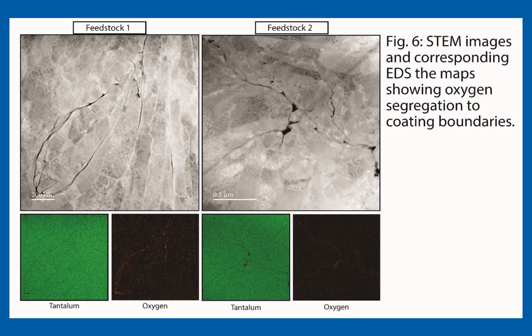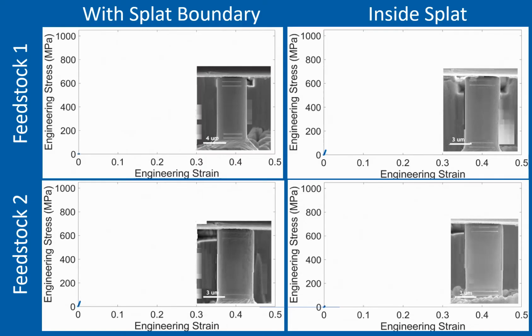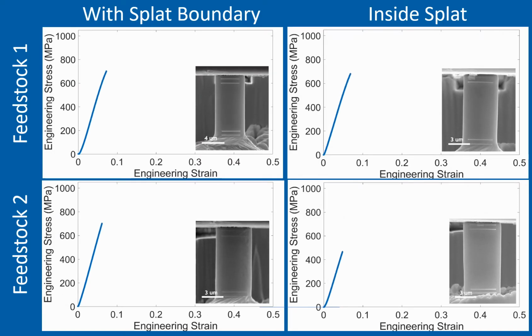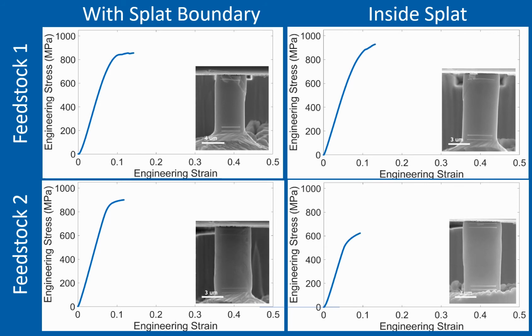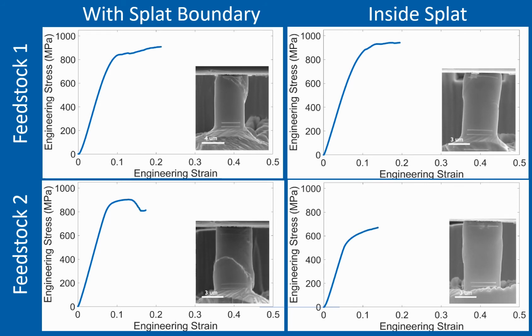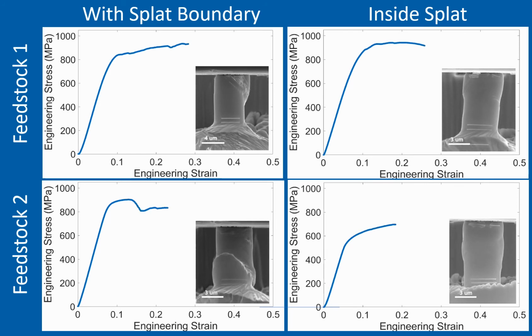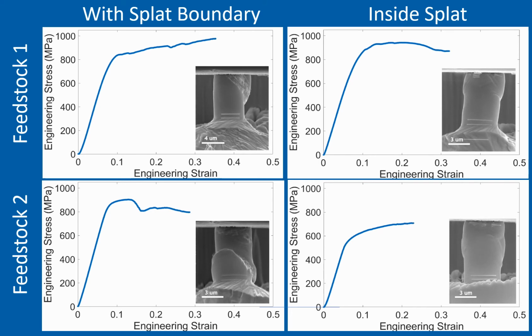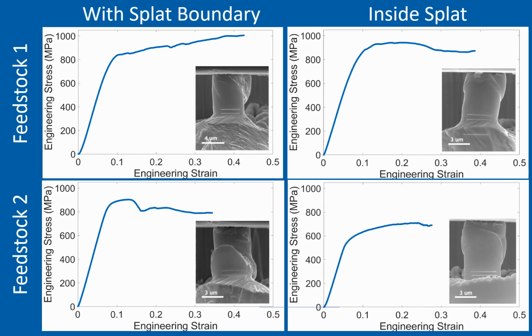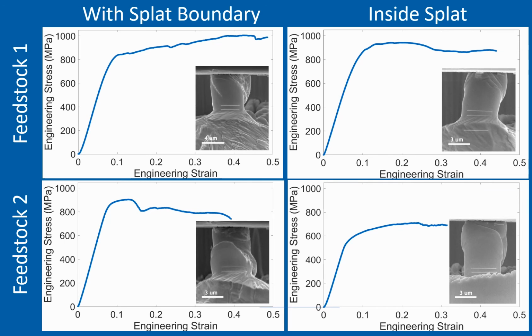STEM and EDS revealed segregation of oxygen to unbonded boundaries within the coatings. However, no clear difference between the two coatings was identified. Micropillars with an aspect ratio of 2:1 were carved and loaded in uniaxial compression. Shear bands and localized failure are consistently observed near the splat boundary regions. Both feedstocks exhibit statistically equivalent strength and ductility at the microscale.